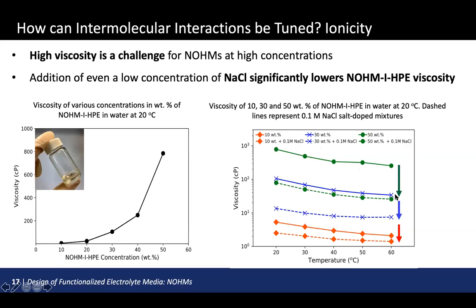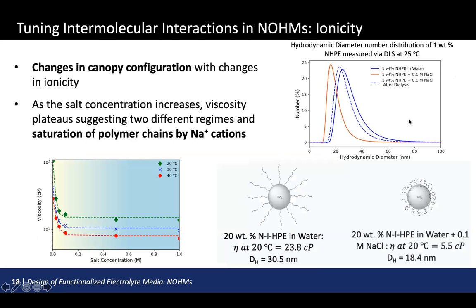And we begin to see very significant decreases in the viscosity of these mixtures. If we note that this is log scale, so that's about an 80% reduction in the viscosity of the NOHMs-based mixture. So this was an interesting finding, but of course we were curious to know what's actually happening here on the scale of a single NOMS molecule. And we used dynamic light scattering, or DLS, to probe this effect.